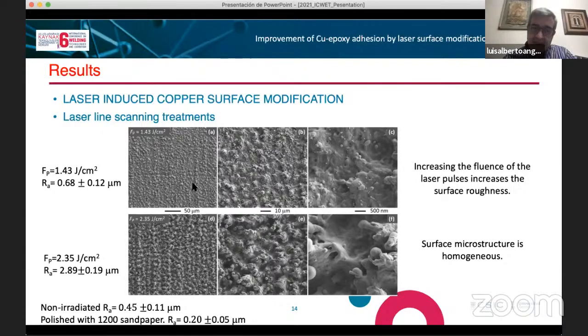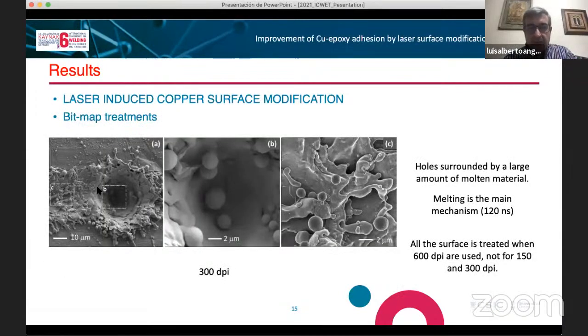What we have seen is that the sample is very homogeneous. The microstructure is very homogeneous in all the treated area, and the color becomes darker. It seems that we have modified the oxidation of the surface. When we use the bitmap, usually what you have is holes like this. You see that the holes are surrounded by a big amount of molten material. Inside the hole, you have some spheres of molten material, and also you have an important amount of this molten material in the area that surrounds the hole.